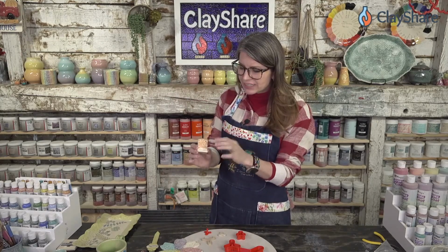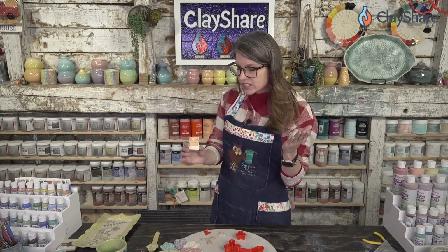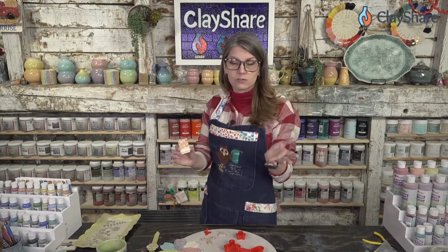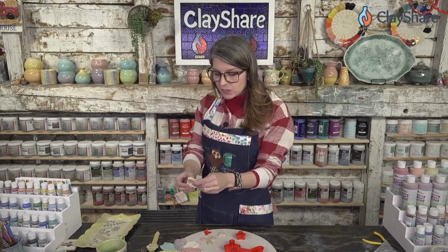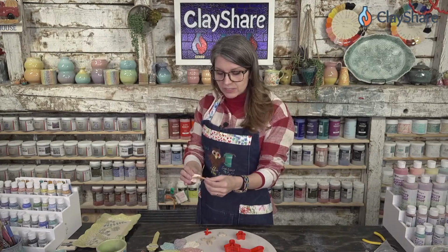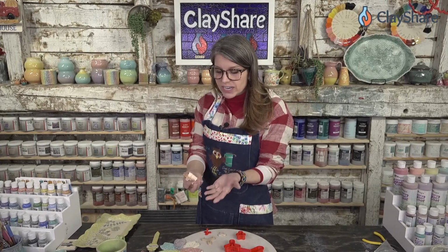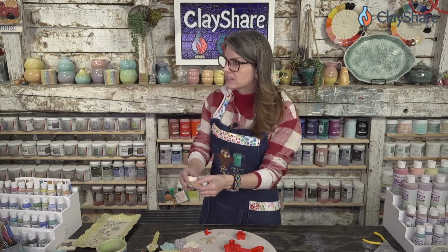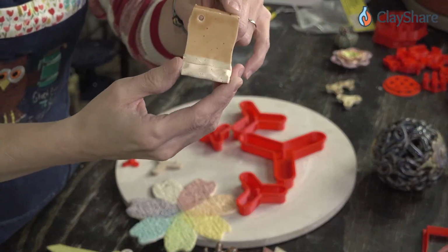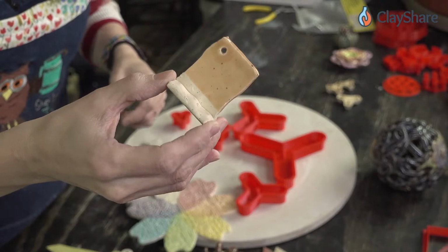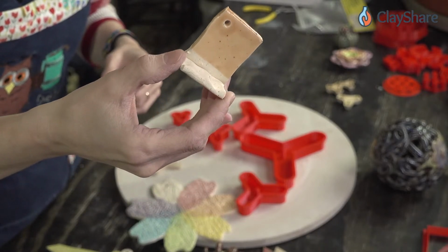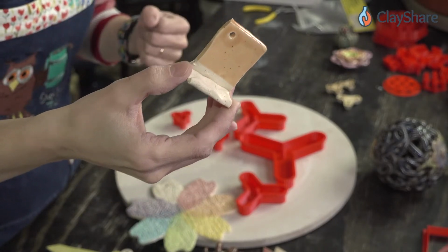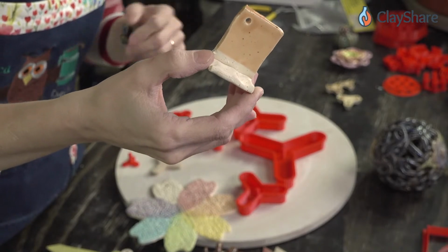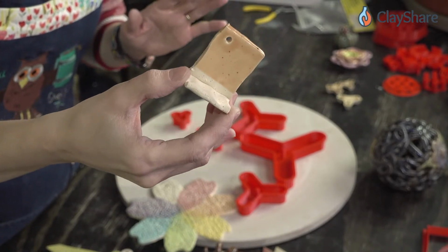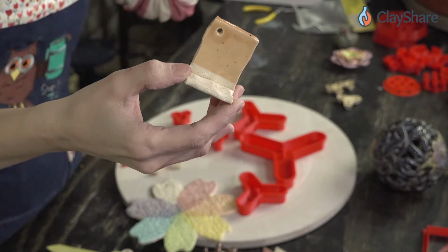So you glaze it, you fire it to cone 5, 6, if that's what the glaze is for. Then you put it back in the kiln, do another glaze firing at a lower temperature, and see what changes, if the surface quality of the glaze changes. So this is one of my celadons. This is Tiger Lily, and here it is. This one was actually dipped, and I fired this again at cone 05. It's fine. It doesn't change at all. It's the exact same as it was fired to cone 5.